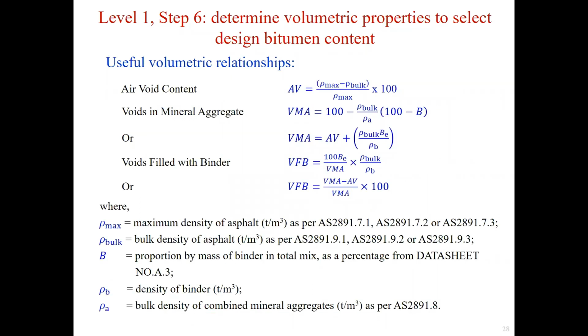Based on the previous figure, we have the following useful volumetric relationships for air void content AV, voids in mineral aggregate VMA, and voids filled with binder VFB. Among these formulas, rho max is the maximum density of asphalt in tons per cubic meter.